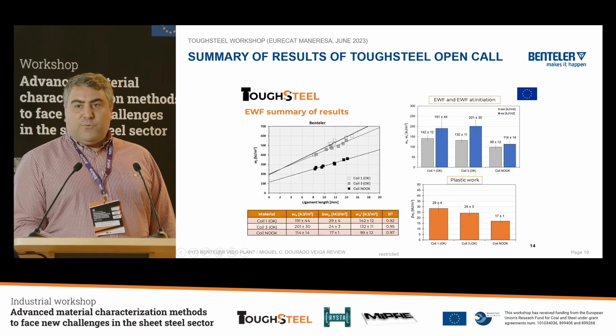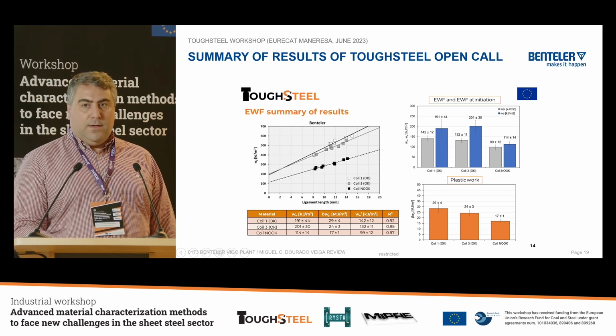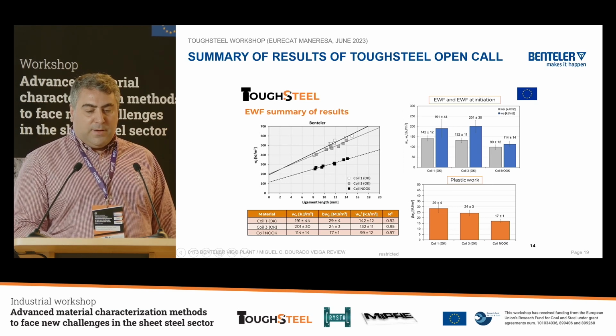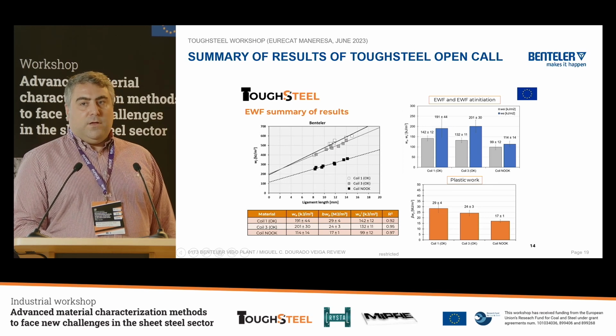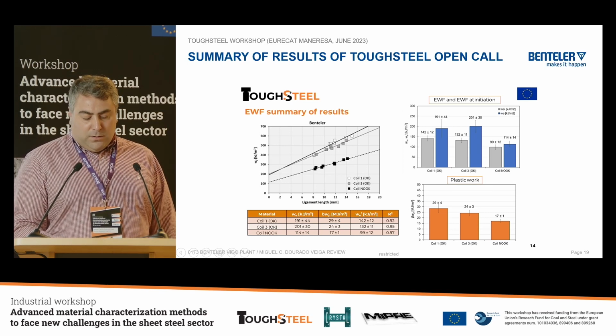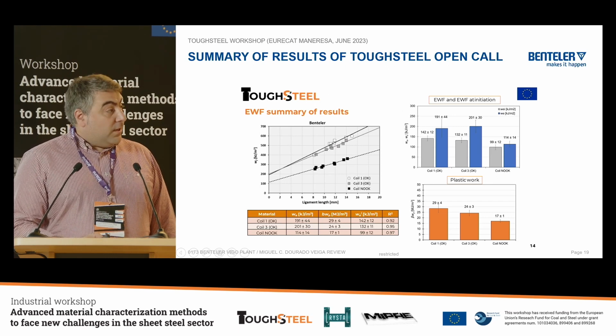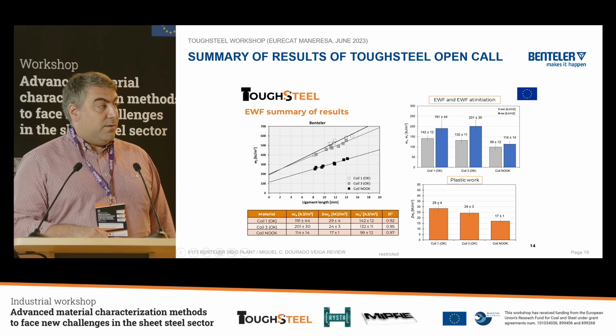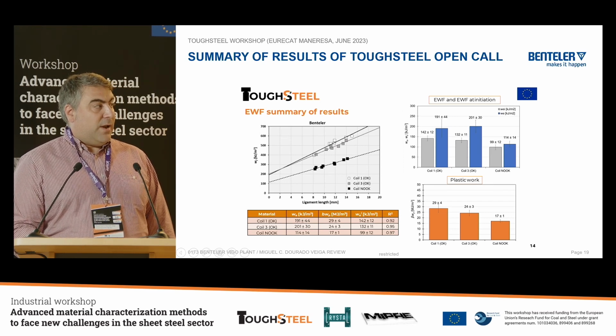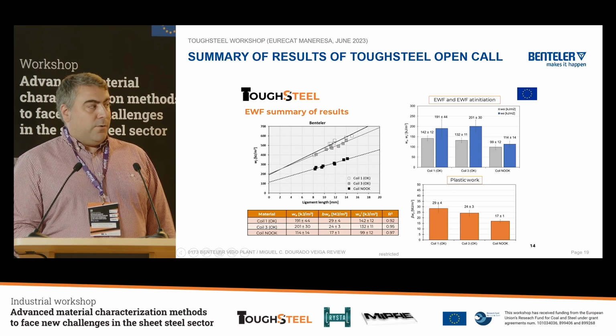We have tested 3 different coils. One of them was a coil with very high scrap rate, and the other 2 were coils with 0 scrap in the Vigo production. And as you can see here, the behavior is quite different. The coil not okay is in black color, and the coils 1 and 3 that were okay are in white and gray color.